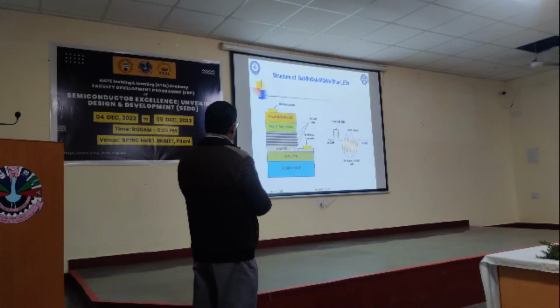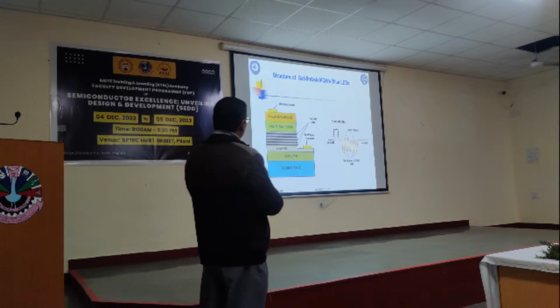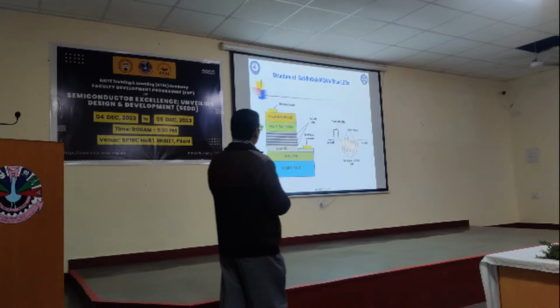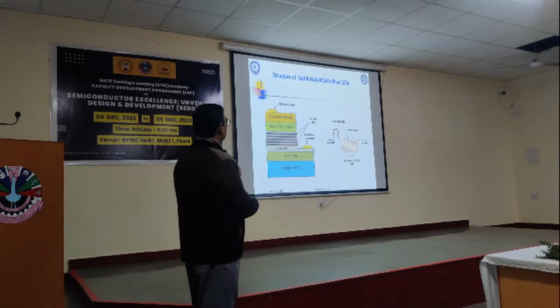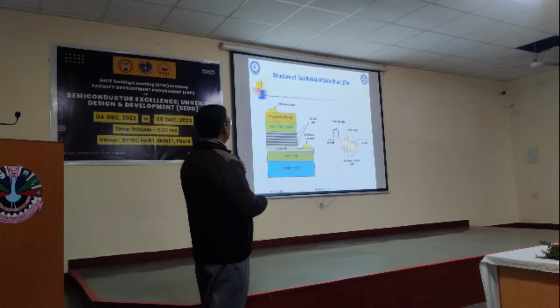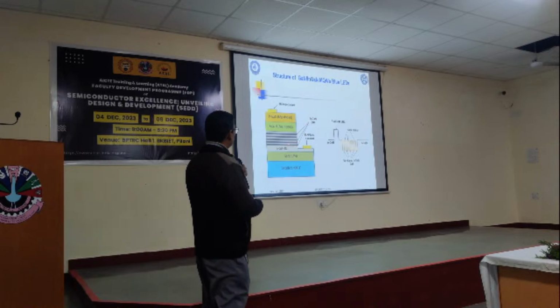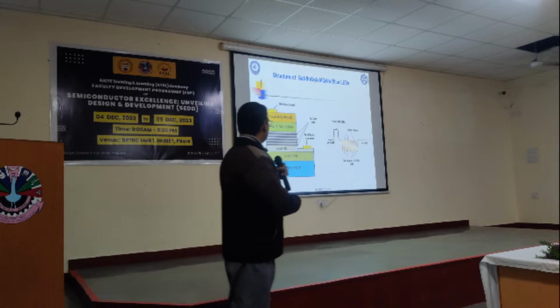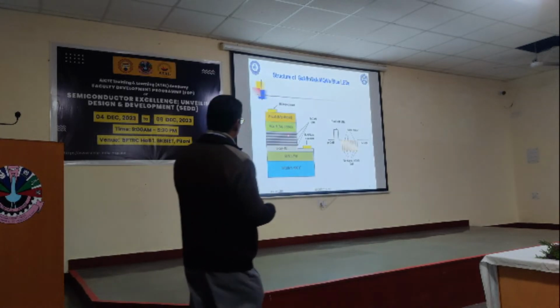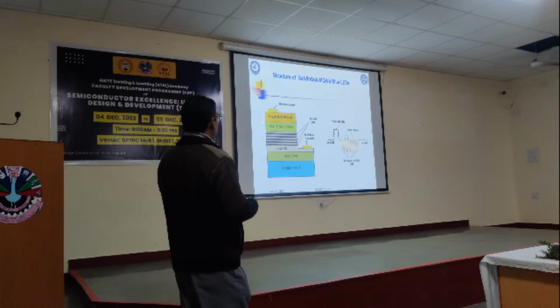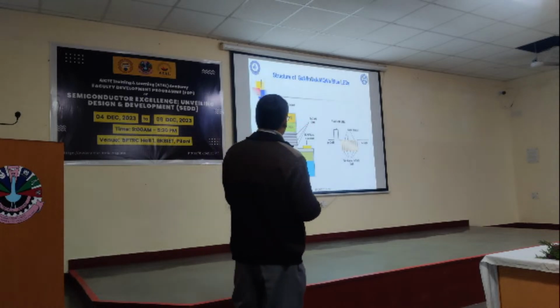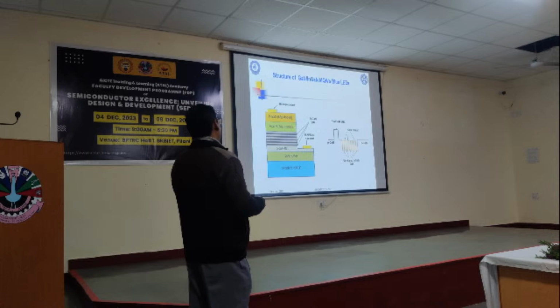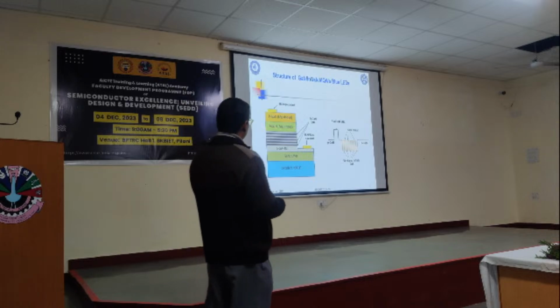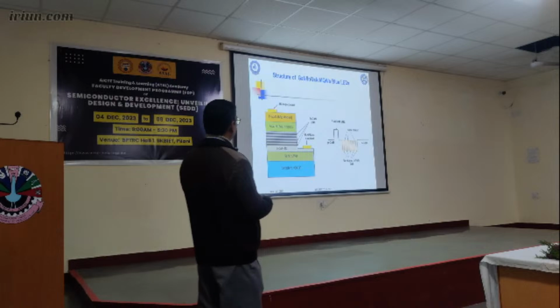So we go for N-GaN with silicon doping. Then we go for the multiple quantum well and barrier region. For the quantum well we incorporate indium composition, and without indium composition, the gallium nitride will act as barrier. We can incorporate 5 to 10 quantum wells and barriers, and after that a certain region of EBL kind of thing, and then we go for p-type gallium nitride. From here we make the contact. So the p contact we make from here, and the n contact we make from here.